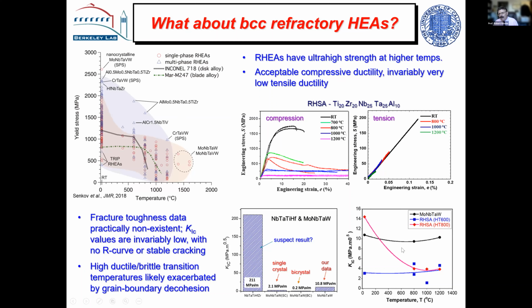But compare that with the ones for the FCC alloys where we had toughnesses of 500. And part of the problem here is that they can embrittle in the boundaries. There's a big problem with decohesion in the boundaries. And the notion of segregation to the boundaries is now different because you've got 4 or 5 elements in there. And so the whole boundary can change rather than just an element going into the boundary. So this is a very interesting field to look at.